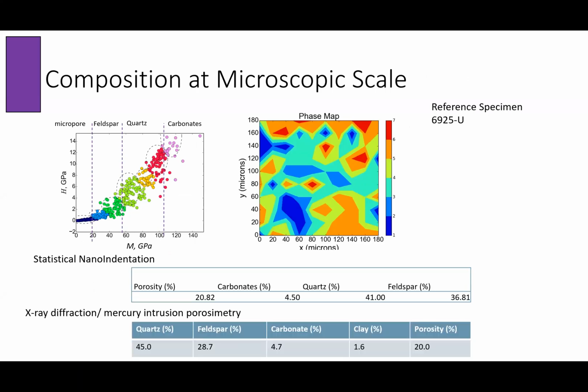What we did is on the unaltered sample, we looked at the phase composition and the porosity, and we compared with X-ray diffraction and with MIP, but we are not able to do what I was talking about with MJ. What I need to be able to do is take my map where I did the nanoindentation and do the SEM mineralogy at the same location. That way, when I go back again to my statistical deconvolution, instead of having just M and H, I can now add elemental composition from the SEM.